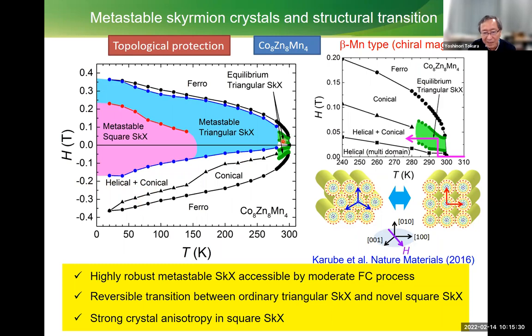However, once the skyrmion is created with a tiny magnetic field, something like this protocol, you just cool down. In that case, we don't have to cool rapidly, because this compound is a mixed crystal with lots of disorder there. So we cool down rather gradually by way of the skyrmion phase, and everywhere there is skyrmion. So this big crystal shows a full of skyrmions by using this protocol. It's a metastable triangular skyrmion lattice, but even more interesting, reflecting the particle nature, the skyrmion crystal shows a kind of crystal structure transition as a function of temperature. It goes down to this kind of metastable square lattice structure. Of course, this is relevant to the magnetic anisotropies.